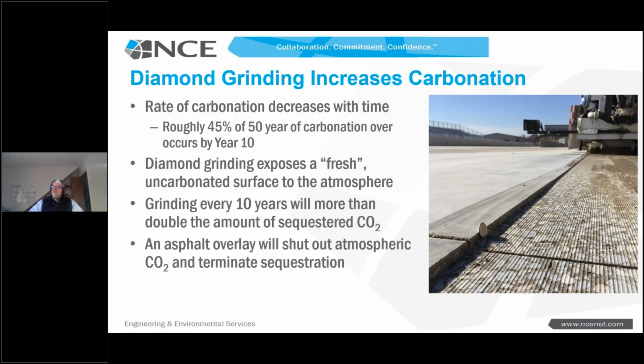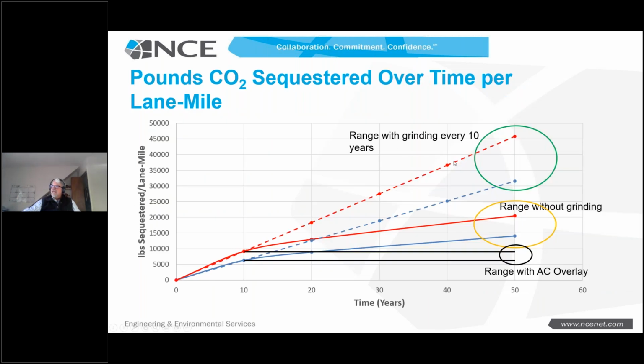One thing I wanted you to think about, though, is in this case, if we diamond ground that surface. So let's say after 10 years, we diamond ground it, ground off the carbonated part, exposing fresh paste. What you will see is the carbonation reaction will resume. And what that might look like is with grinding every 10 years, we're going to end up sequestering a heck of a lot more than double, almost triple the amount of CO2 that gets sequestered in that concrete. On the other hand, if our choice of a fix in this case was let's seal the concrete up with an asphalt overlay, we basically ceased carbonation.